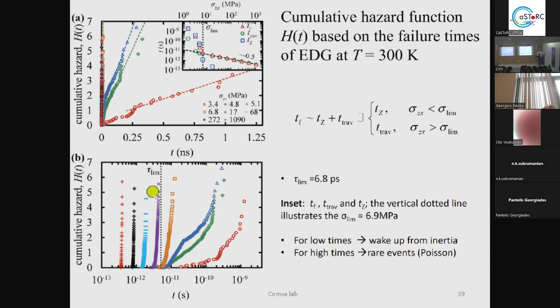These two plots are the same. Their only difference is that one is linear, and the second is semi-log. Someone could say that we have a zoom in here on the right of the whole plot. This plot is a zoom in at very small times, as you can see. And putting different stresses, with different colors, we see that we have different slopes. And so for small stresses like this one here, we have a slope like this, which tells us that at some time, the failure will happen, sometime.